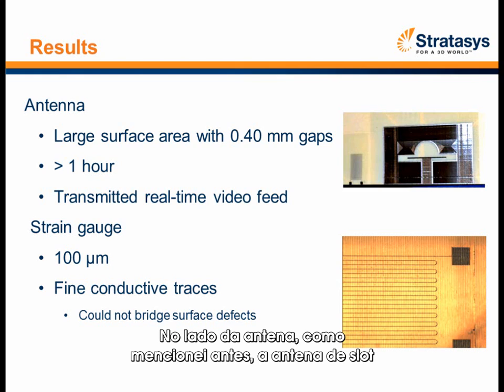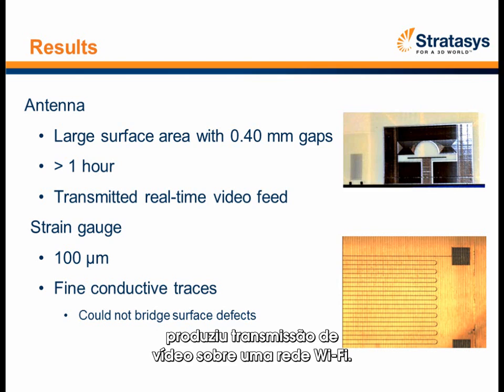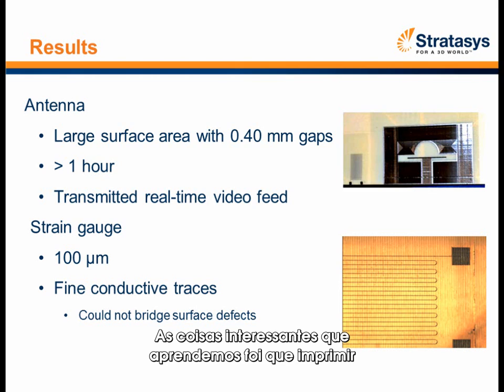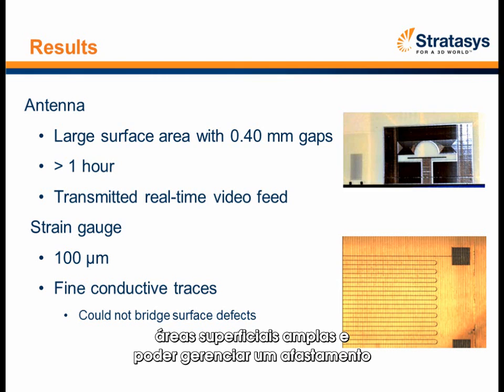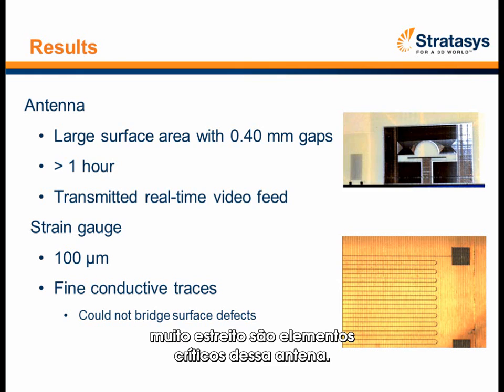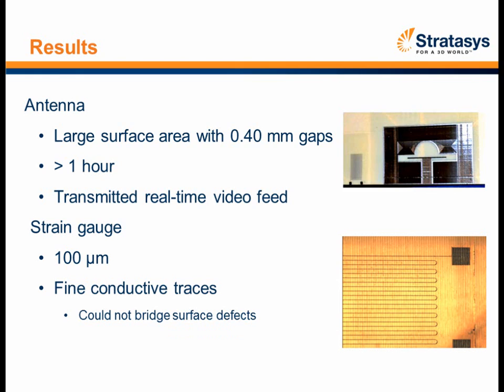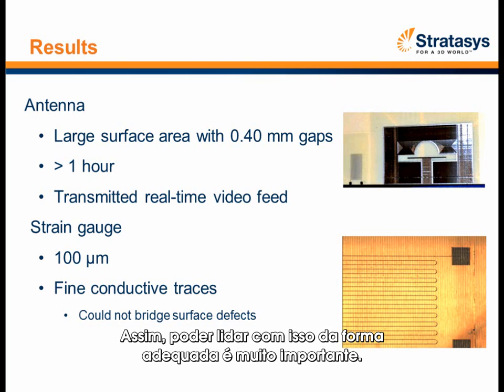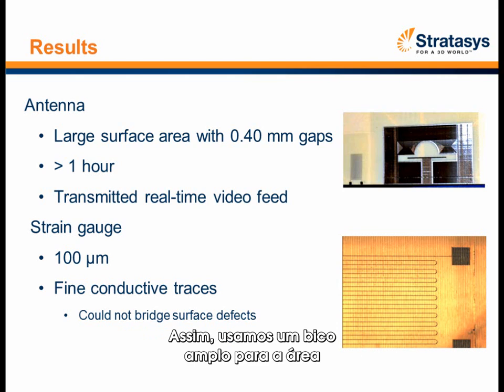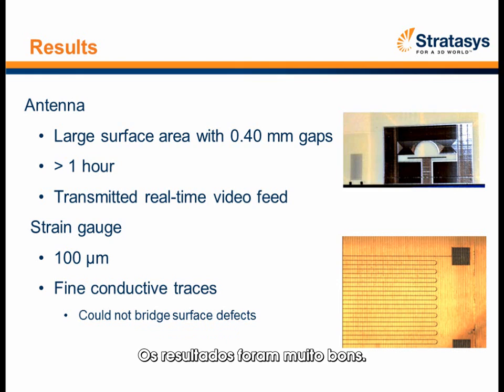On the antenna side, as I mentioned before, the slot antenna produced video quality transmission over a Wi-Fi network. The interesting things that we learned out of this is that printing wide surface areas and then being able to manage a very narrow gap, those were critical elements of this antenna. So being able to manage those appropriately is very important. So we used a wide nozzle for the area and then a narrow nozzle to come in and print the very fine features. Got very, very good results.